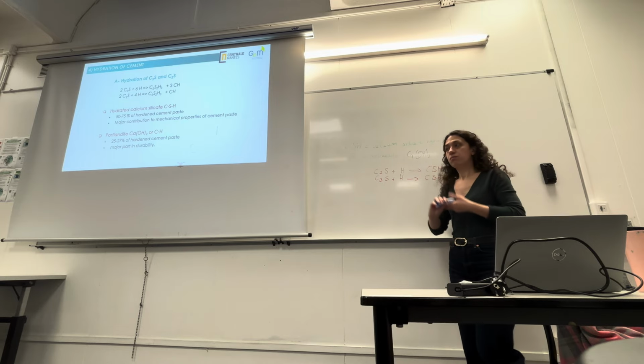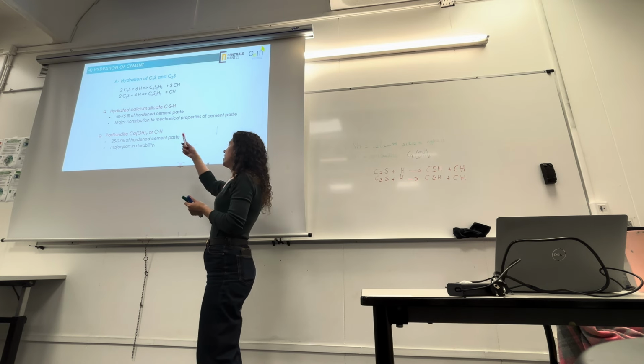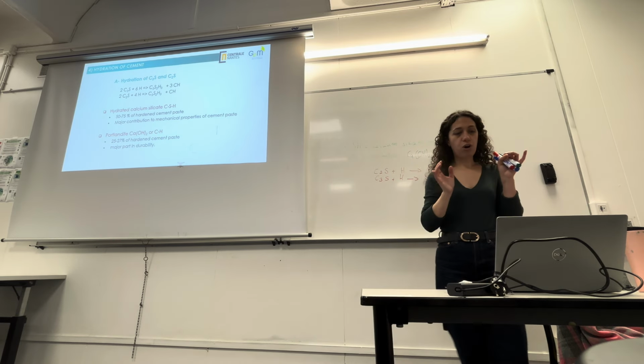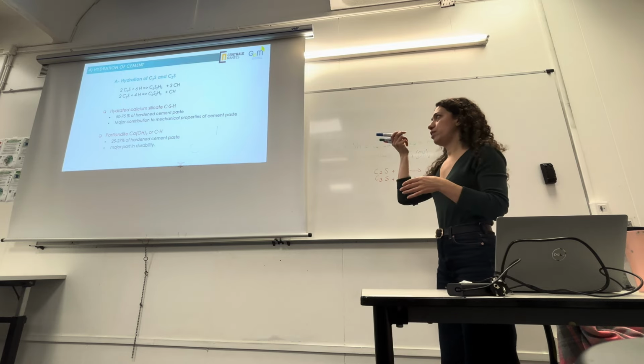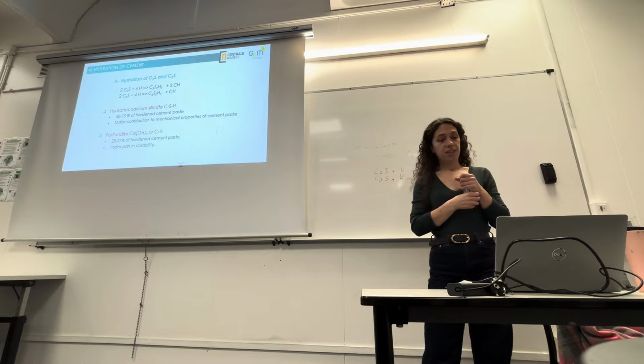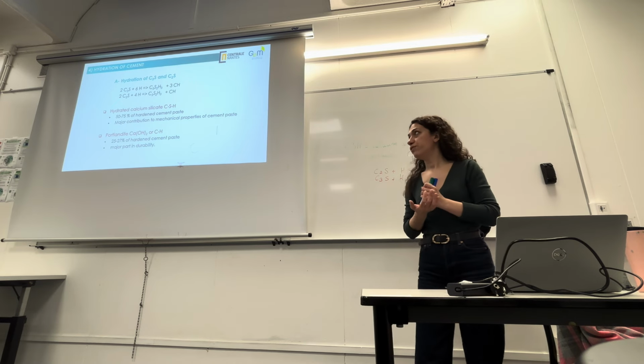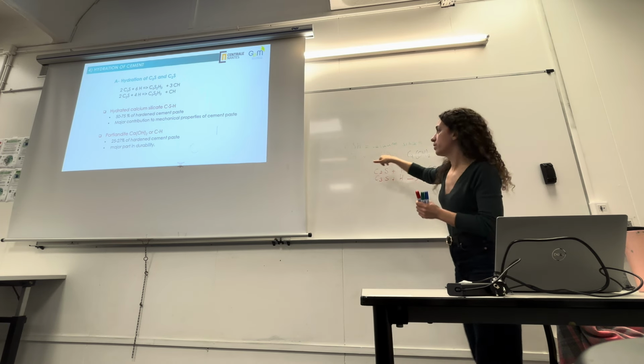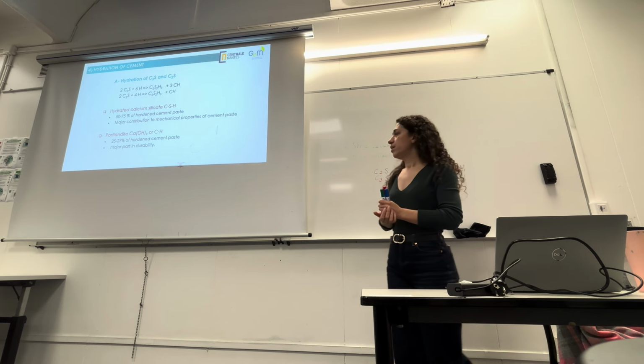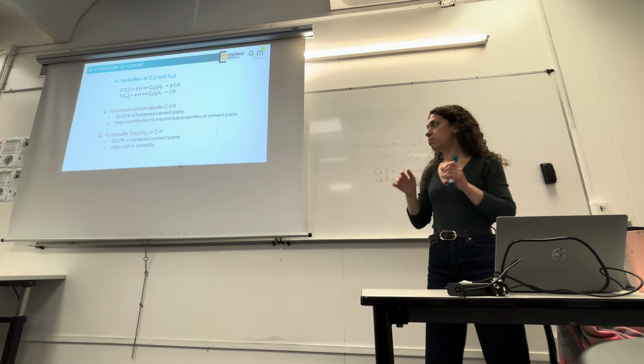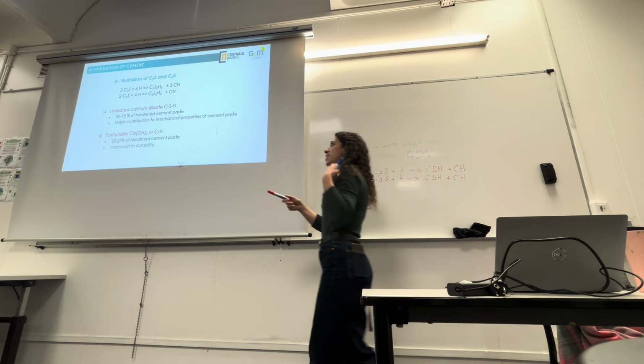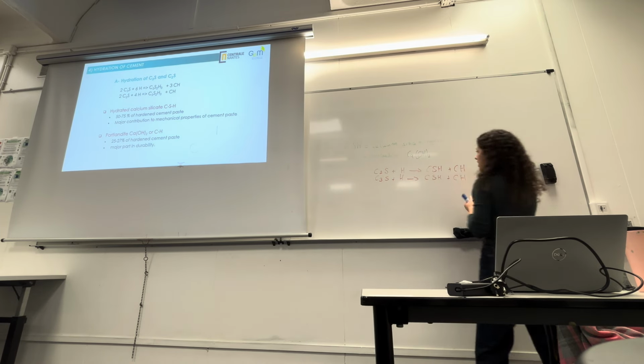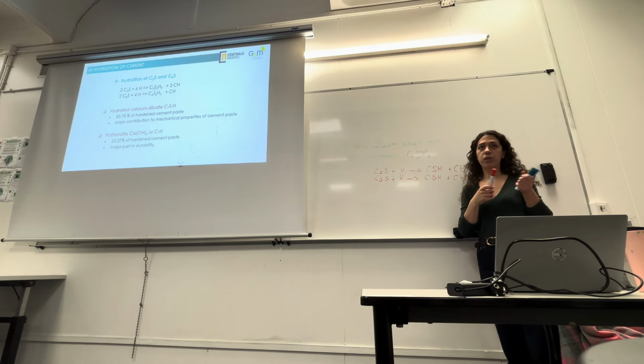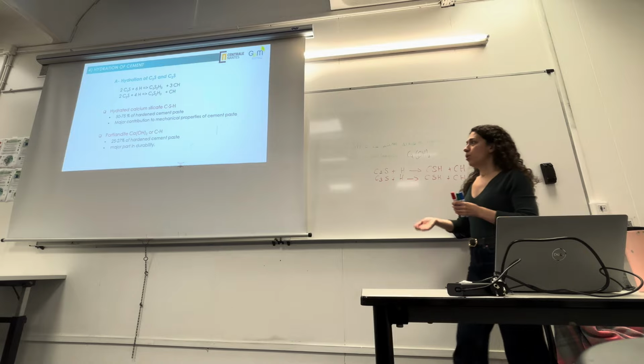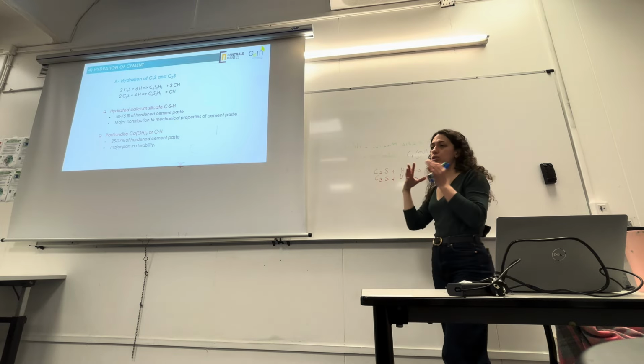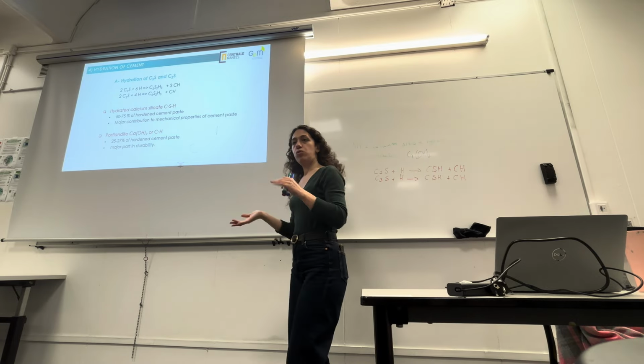Okay. So, what is CSH? Hydrated calcium silicate. This is the main compound of the hydrated cement paste. It forms 50 to 75% of hydrated cement paste. And it gives the major contribution to mechanical properties of cement paste. Then we have Portlandite, Ca(OH)2, CH. It makes roughly 25-27% of hydrated cement paste. And once again, when I say hydrated cement paste, we have to understand that it's only clinker, and later we will see the case when there is a secondary cementitious content. But here, Portlandite is 25-27% of hydrated cement paste, and it plays a major part in durability.